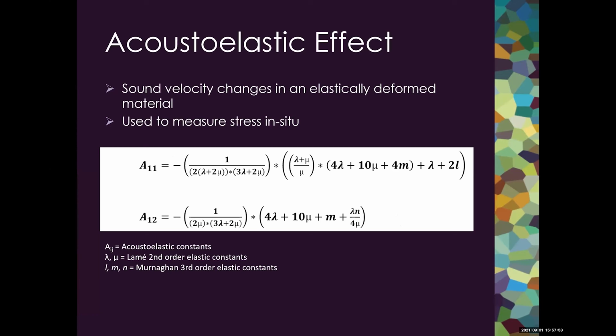So since these are the first measurements of the acoustoelastic constants at high pressure, we don't have any comparable measurements to compare our results. And so it's informative to make some form of comparison. So we've done this with measurements of metals at low pressure. Most measurements in the literature report the third order elastic constants rather than the acoustoelastic constants. And so we calculated the P and S wave acoustoelastic constants as a function of the second order elastic constants reported in literature. So we have our lambda, mu, and our Murnaghan third order elastic constants l, m, and n.